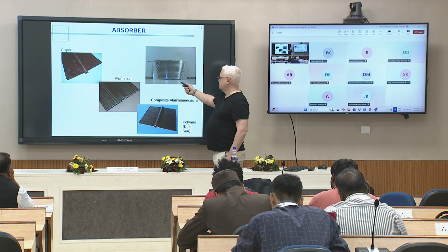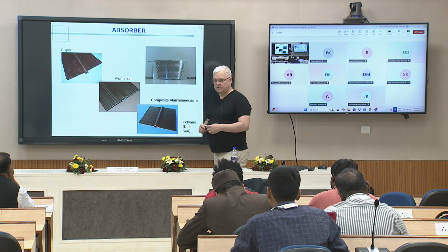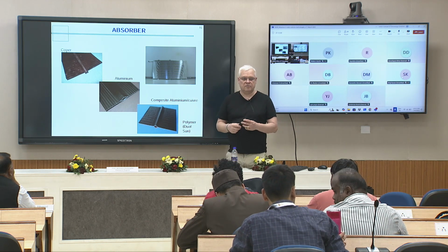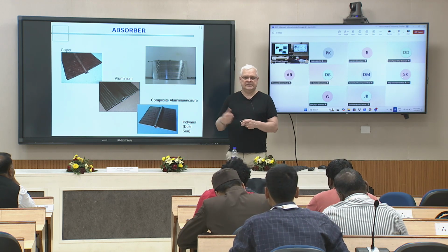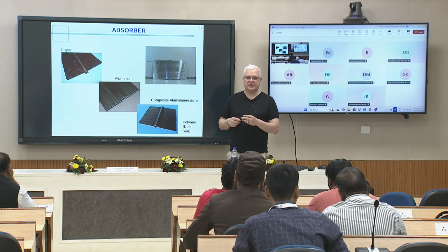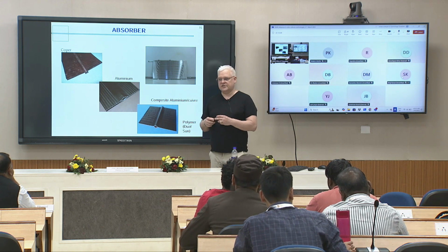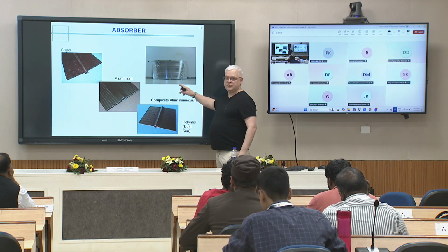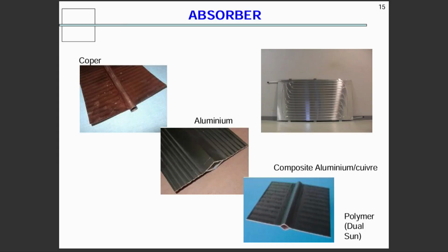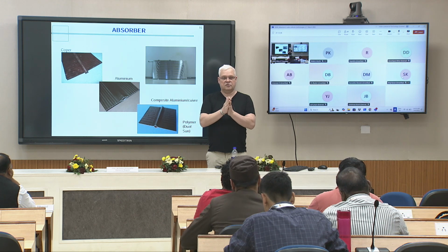This is manufactured as a roll bond. It is a roll bond technology. It is the kind of heat exchanger, not the shape, but the kind of heat exchanger that we find in a fridge. In the fridge, inside the wall of the fridge, you have an aluminum heat exchanger that has a particular shape, made with the same technology. So this technology is called roll bond.